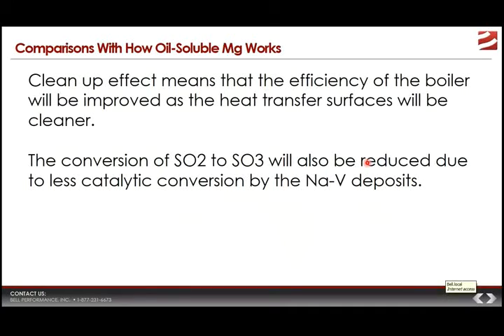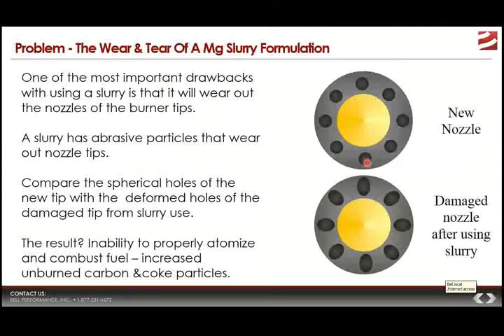Now, if you clean things up like that, then you're going to have a more efficient boiler. You're going to have cleaner heat transfer surfaces, which means the heat transfer is going to be where it needs to be. And, of course, you're not going to have conversion of SO2 into SO3 because those deposits are not around to catalytically influence them by their physical presence. So oil-soluble magnesium is more effective at combating existing deposits.